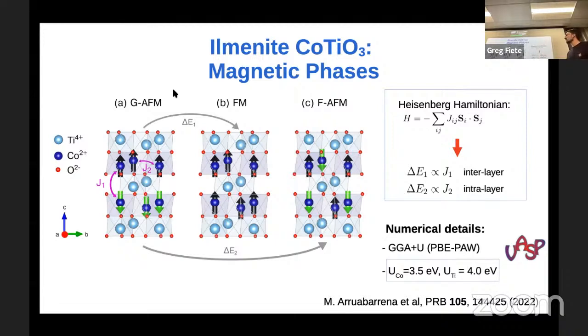magnetic configurations we have, which are the experimentally observed ground state, the GAFM. It's a configuration that consists of ferromagnetic cobalt planes that are antiferromagnetically coupled in the z-axis. Then we also consider the ferromagnetic case in which all the spins in the system are aligned, and the so-called fully antiferromagnetic case in which inside the cobalt layer, we also have antiferromagnetism. By means of this model, these Hamiltonians, and the total energies we extract from DFT, we are able to calculate these magnetic couplings and relate them to these energy differences.